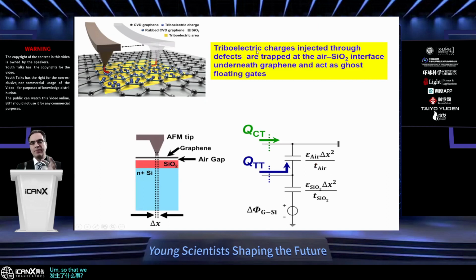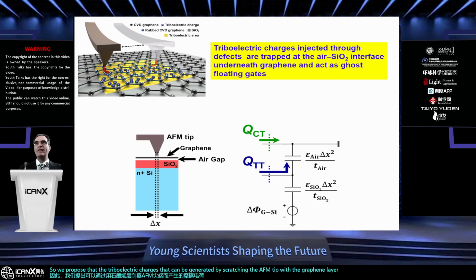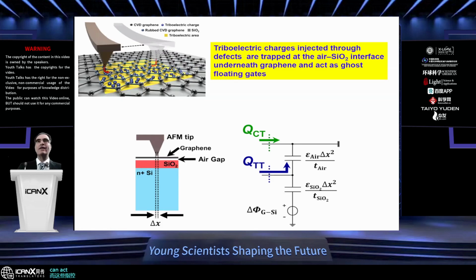We propose that the triboelectric charges that can be generated by scratching the AFM tip with the graphene layer can be very easily injected through the defects of the graphene, because graphene is so thin, just one atomic layer, so tunneling is very easy and effective. And these charges can tunnel through the graphene, they can be trapped at the air silicon oxide interface underneath graphene, and those charges can act like a ghost floating gate.